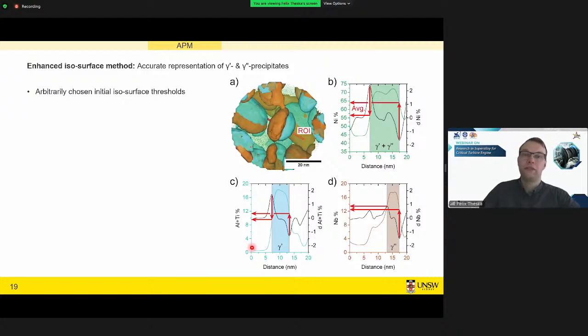Okay, now we have reconstructed our data. The next challenge is how do we represent these particles? Because what we see is usually just points of each atom. And what we see here in these brown and turquoise surfaces are so-called isosurfaces. And basically we can do with them whatever we want. We can set them to, for example, 10 atomic percent niobium. Anything above this value will be enclosed by this surface. But how do we know that this value is a correct value? Because if we make it larger or smaller, we can also make the particles appear larger and smaller, which is of course difficult if we want to have an accurate size of them.